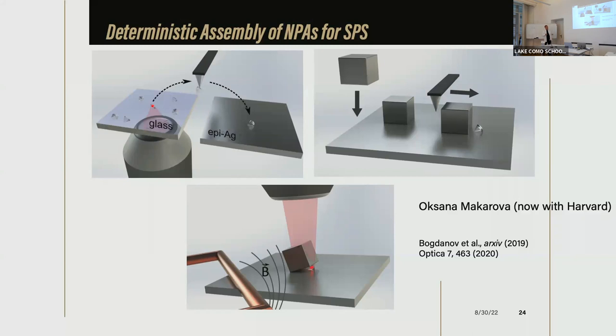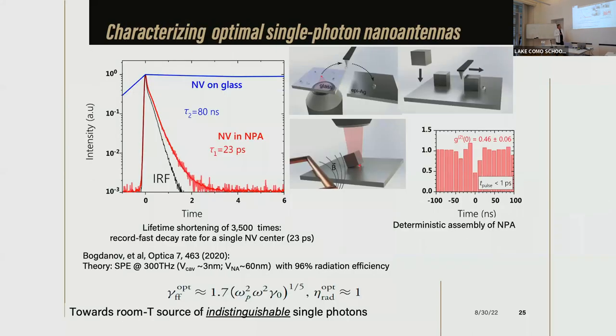Importantly, in this case, it sits exactly at the edge of the cube where the Purcell enhancement is the largest, as our simulations show. In this case, we obtain actually a record short lifetime, which was only 23 picoseconds, and 3,500 times speed up in terms of lifetime shortening.